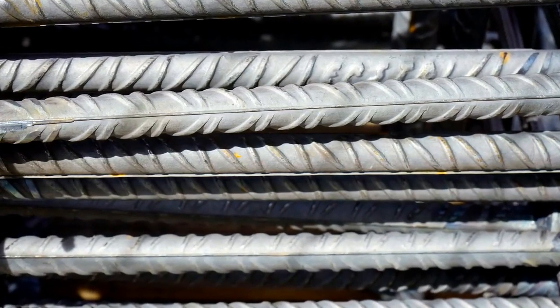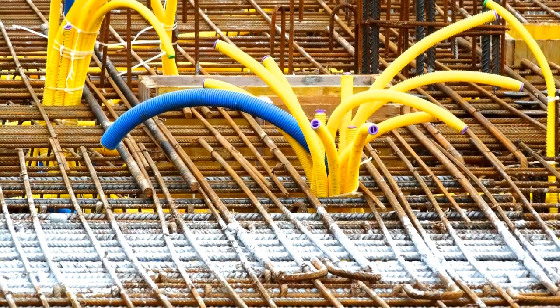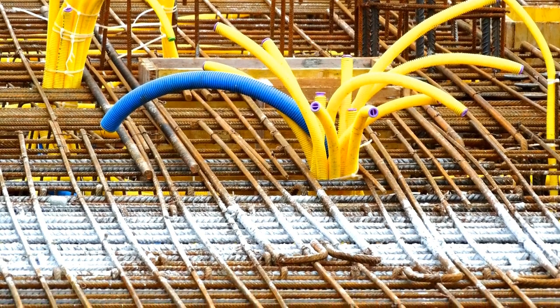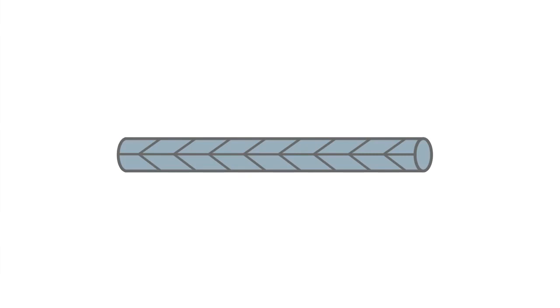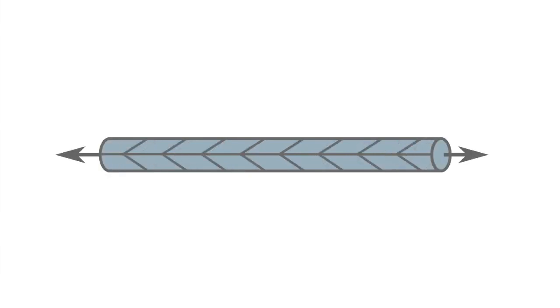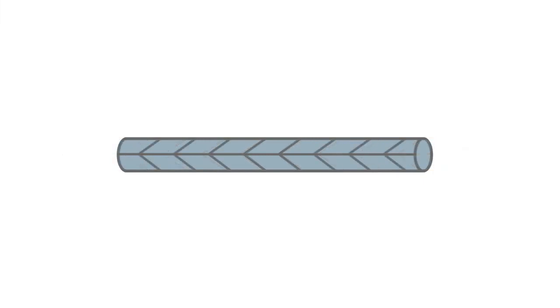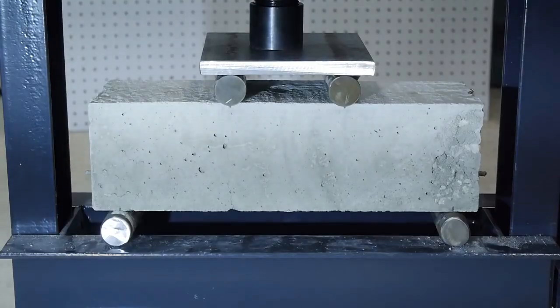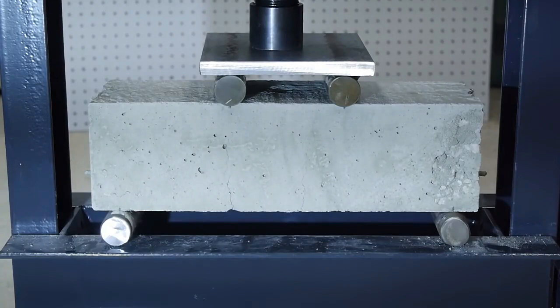Rebar works great for most reinforcement situations. It's relatively cheap, well tested, and understood, but it does have a few disadvantages, one of the major ones being that it is a passive reinforcement. Steel lengthens with stress, so rebar can't start working to help resist tension until it's had a chance to stretch out. Often that means that concrete has to crack before the rebar can take up any of the tensile stress